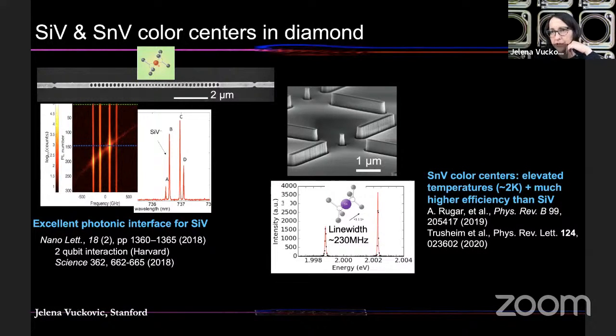And then with tin vacancies, in recent work, both in collaboration between Dirk Englund's group at MIT and Mete Atatüre at Cambridge, and also our recent work, we did a spectroscopy of the system. We've shown that the energy level structure looks exactly as theoretically predicted. So this is a very recent work. I mean, this new color center has emerged over the past couple of years. We've shown that we have very narrow linewidth of the transitions, even when we embed them in the structures, which is a very important ingredient for moving forward with this particular color center.